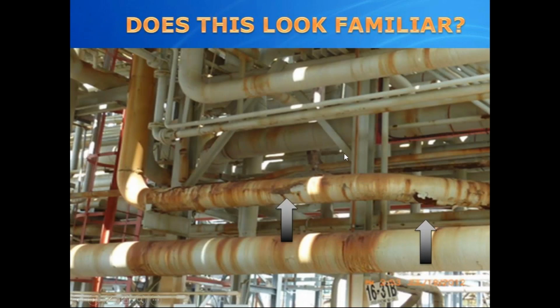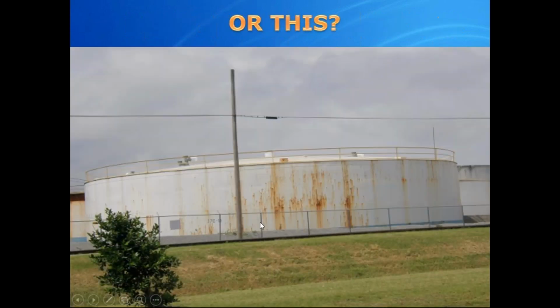Okay, I have a few photos to show you. Here's a pipe rack where you can see some major problems taking place. First of all, where the arrows are pointing, you have complete coatings delamination from the 3 o'clock to 9 o'clock positions. On the piping itself, you have corrosion at the interface of piping and pipe supports, right around this area here on the pipe supports, and corrosion at edges of angles, like here, and rust stain from overhead corrosion, of course. That's predominantly what you're seeing there, a lot of rust stain.